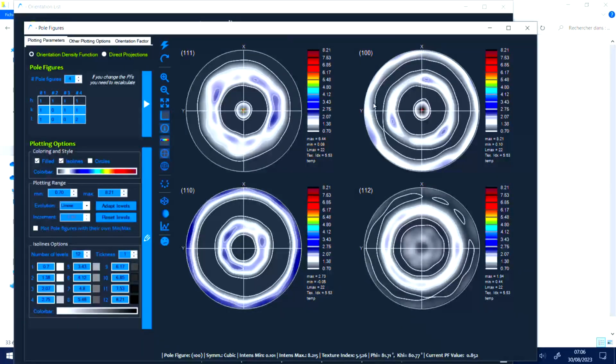There are only three 100 directions in the crystal, you know. So we can have 3 circles. 110, there is more, but they almost coincide here. And 111, we can distinguish finally on the figure only 2. This is common, and in here there are some more.